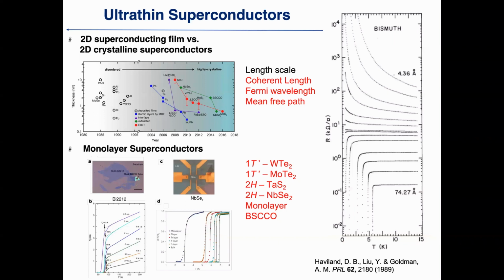But on the other hand, if you talk about phase transition, there are some subtle points, because once the system becomes not superconducting, you are entering some other length scale, which is called the Fermi wavelength. And in the metallic system, the Fermi wavelength is normally very, very short, on the scale of a few angstroms. So basically, once you have a phase transition, then immediately from a 2D superconductor you enter a 3D metal. So there are some subtle points there, and I cannot go very much into detail because this is a spin-related talk.